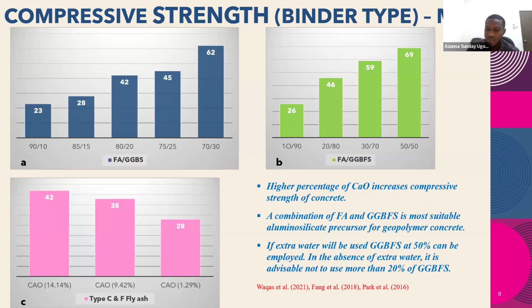Why I said this is, for now, there is no determined percentage or ratio for GGBS or fly ash in any of the mixes, in any of the literatures. So the mix ratio has not been standardized. So it all depends on your desired strength and the desired purpose or application of your structural element. If you need early strength, then you introduce slag at a higher percentage so that your calcium oxide will be a bit high in your concrete. However, if you don't need very high strength, you can reduce the percentage of GGBS and use a higher percentage of fly ash.